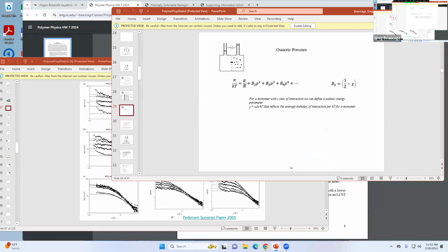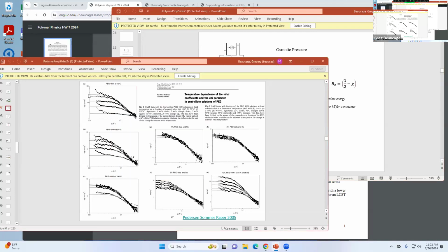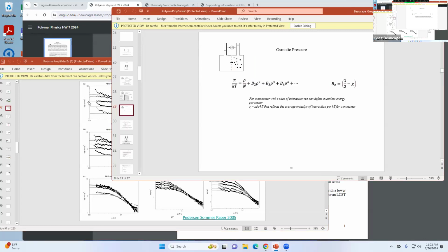Because it's going to be pi over rho, that term drops out and you just get B2 for the first derivative. So this intercept on this plot gives you 1/B2. That's an easy way to measure B2 as a function of concentration. You change the concentration, measure that intercept, and you get the thermodynamics directly from how bright the light is.